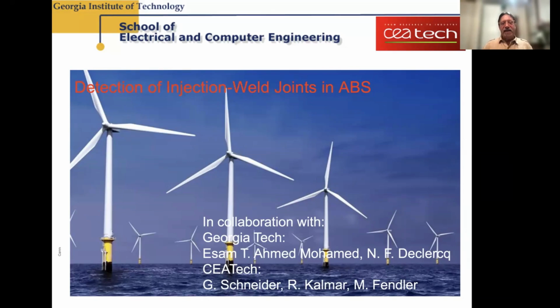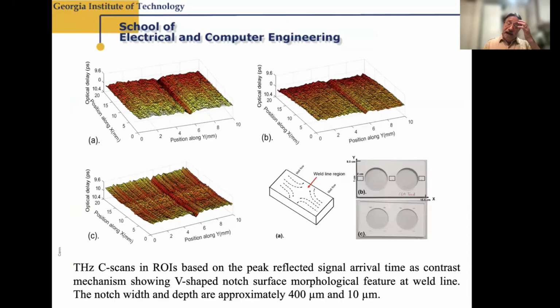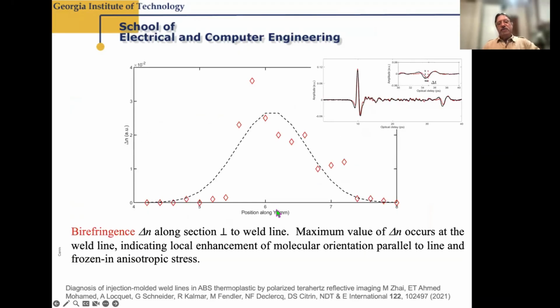the structure fails mechanically. So it turns out that at the weld joint, the different flows meet, and we can have some frozen-in anisotropy of the polymer. And that frozen anisotropy can be used to detect some terahertz birefringence, and therefore we can determine the location of that weld joint. So this is an example where we really can't see the weld joint visibly. There's no kind of valley, nothing we can see easily visibly, but we can see it with terahertz. So this uses the polarization of the terahertz beam.